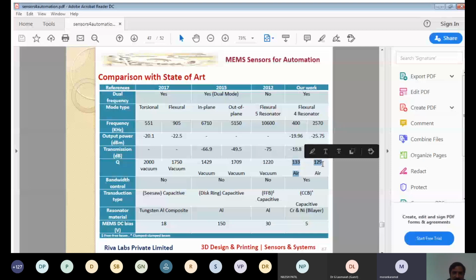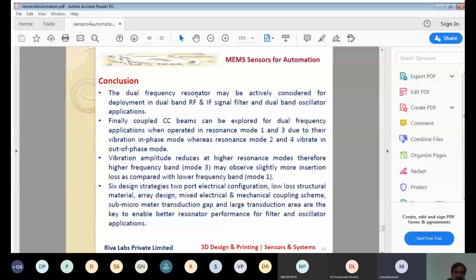So this is a comparison of all this work done from the IEEE transactions. And from the conclusion, what I would say is that the dual frequency resonator may be actively considered for deployment in dual band RF and IF signal filter and oscillator applications. The CC beam can be explored for dual frequency operation for mode 1 and mode 3, whereas modes 2 and 4 vibrate in out of phase mode. So as I showed you in the current output, modes 2 and 4 vibrate out of phase, while modes 1 and 3 vibrate in phase.